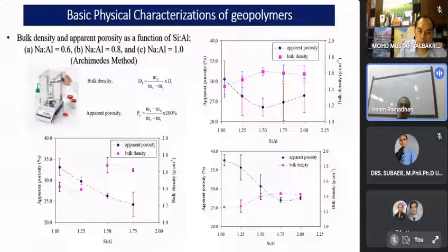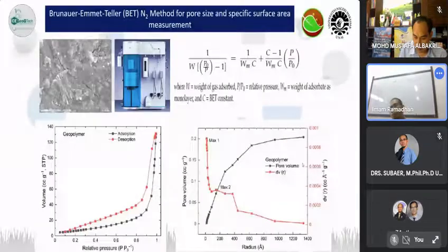And if you want to study further the more advanced information about the porosity of your materials, then you need to access the instrument or technique for surface area as well as pore size or pore distribution measurement by using the BET method, Brunauer, Emmett, Teller, because by using this method you can actually study the porosity down to micro, meso, and nano pore sizes, which is not possible to get information on by using the Archimedes